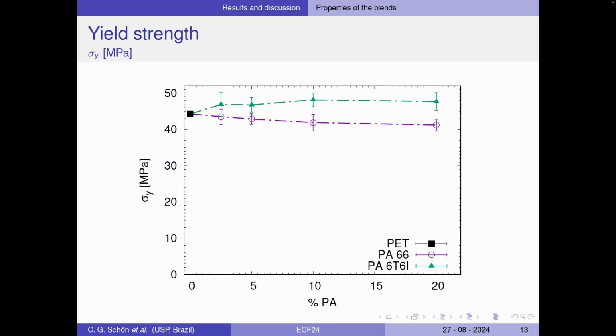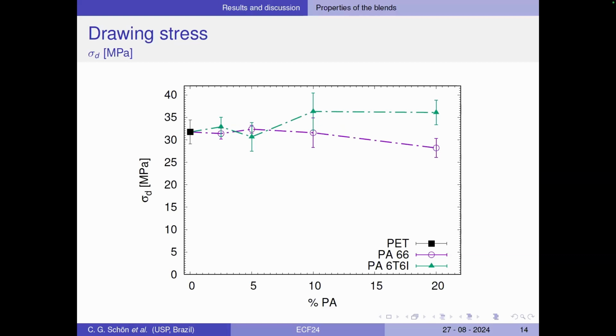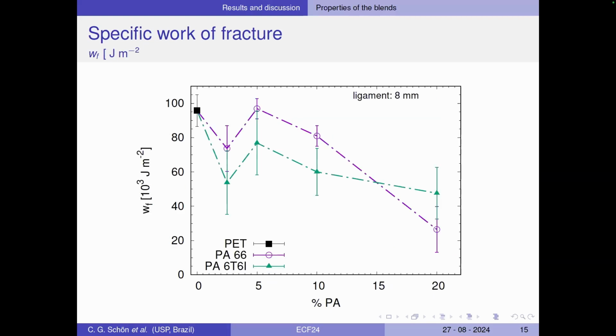Here is the first result for the maximum load. Actually, it's a very good thing when we mix two polymers and nothing happens. It's a very bad thing to report this in a conference, because actually we see that there is almost no effect of PA on the strength of the film. A slight increase for this compatible resin, which is of course much more expensive than the commercial one, and a slight reduction for the commercial. The same happens with what we call the stretching stress. Also no visible differences.